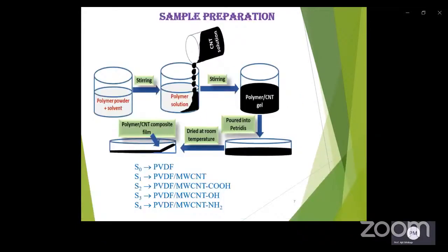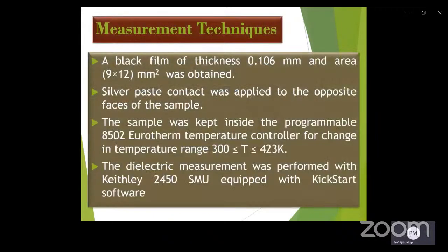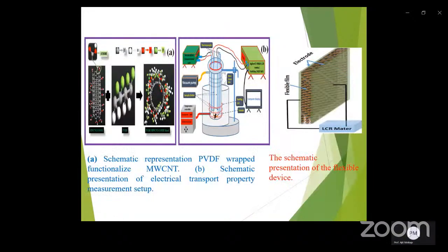The samples are prepared by a simple solution casting route, which is described in the figure. The prepared samples are labeled S0, S1, S2, S3, and S4. A film of thickness 0.106 millimeter and area 9 by 12 square millimeter has been prepared. Silver paste contact was applied to the opposite faces of the sample for electrical measurement. The experimental setup for the dielectric measurement for the temperature range 300 to 423 K is described in the figure.